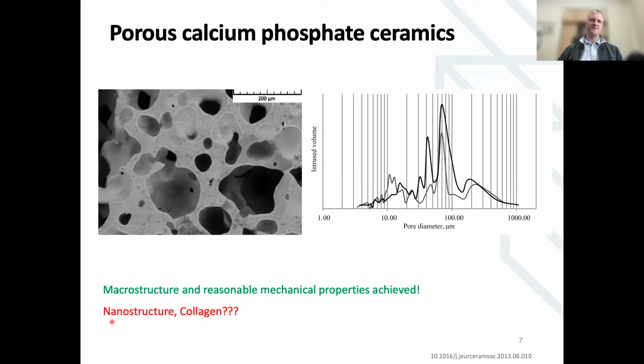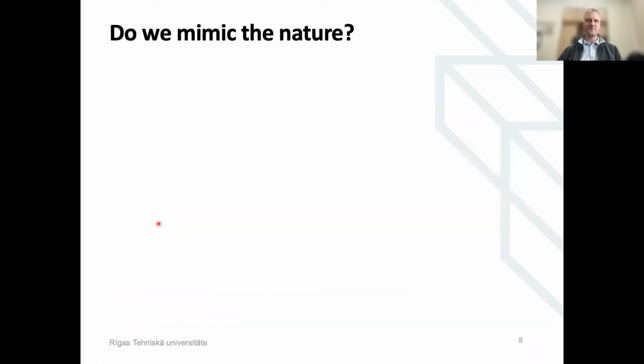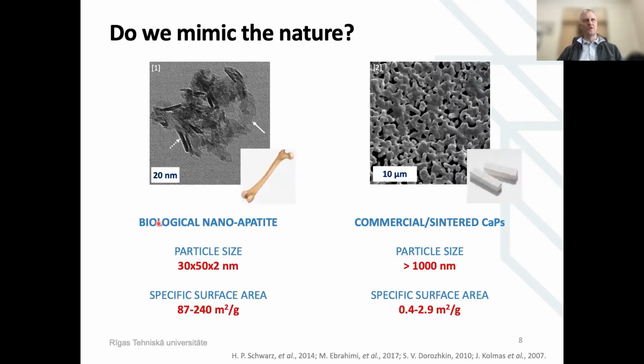And the biggest problem is that during the sintering, we lose the nanostructure. And we don't have the organic phase. So in this case, after the sintering, it is really the ceramic alone. So the question: do we mimic nature? Looking back at what we have in nature, in our bones we have hydroxyapatite nanoparticles. So this is the size range. And there is one specific parameter that can be measured for all nanoparticles, the specific surface area, which is really related to the particle size of the material. As the particles get smaller, the specific surface area gets bigger. And this specific surface is later related to absorption and desorption of proteins and bioactive molecules in the body, and that is very important.